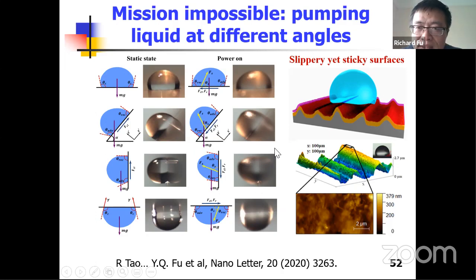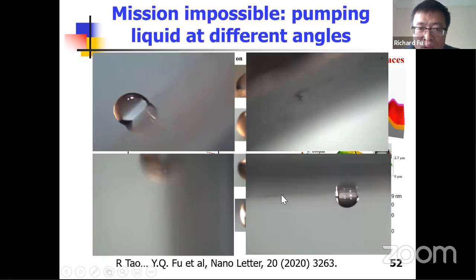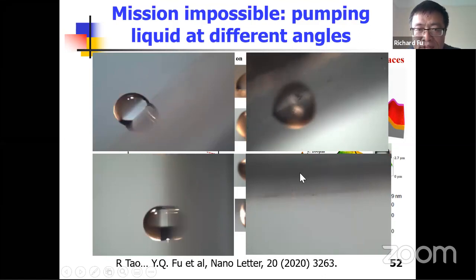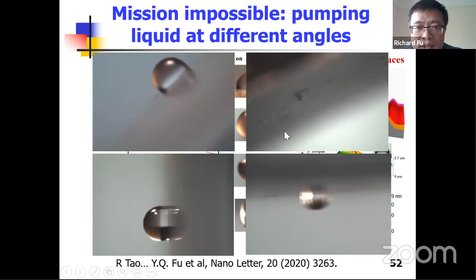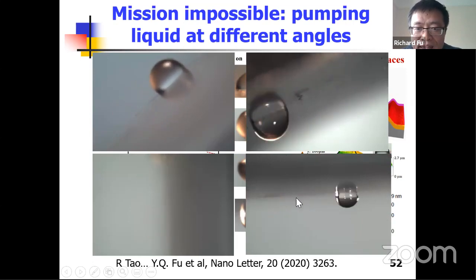So superhydrophobic designs are not good for this application because the droplet easily falls down if you don't drive it efficiently. The aluminum surface is very rough, with microscale roughness. The thin film zinc oxide, a piezoelectric material, has nanoscale roughness. And if we deposit a layer of hydrophobic coating, we can realize a slippery and sticky surface, which is the best for this kind of wearable application. So we deposit the film and make a device on aluminum foil, and we can demonstrate that whatever the angle, we can pump the droplet easily.